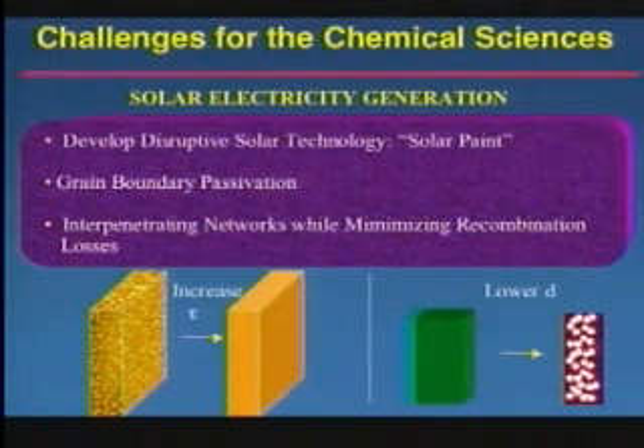The physics of this is that if you were to take silicon and use 1 micron grain size, all the grain boundaries are recombination sites. And the reason for that physically is all those surface silicon atoms know that they're not bonded to 4 other silicon atoms in the bulk. And so every time an electron hole pair gets to one of the ends of the stepping stone, it doesn't hop across it. And in fact, it just recombines.